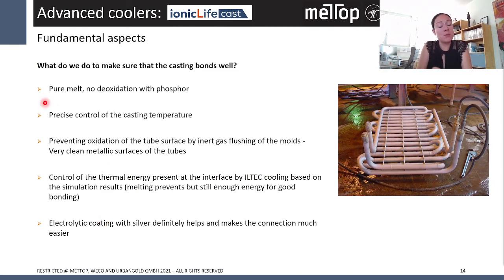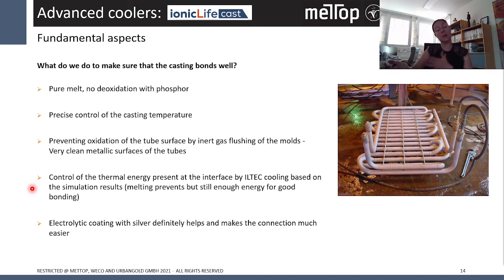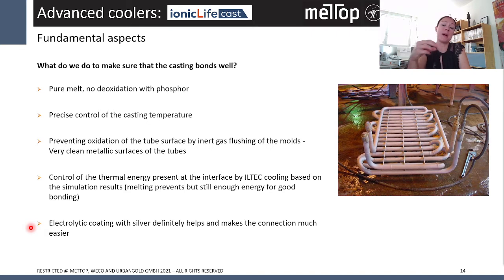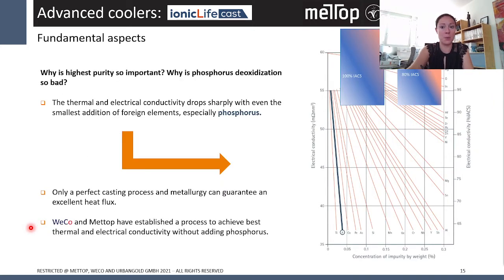What's also nice about coolers produced with this technology is that you don't have any deoxidation with phosphor. You have very precise control of the casting temperature. You can control the thermal energy because you can control the cooling, so you can either drag out more heat or less. And with the help of the electrolytic coating with silver, the copper pipes are coated with a very thin layer of silver, which gives an extremely nice bonding between copper pipe and copper matrix.